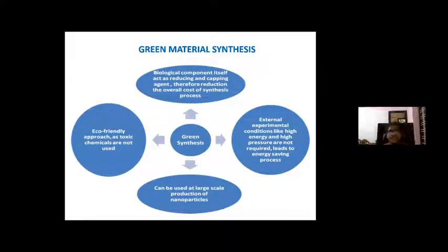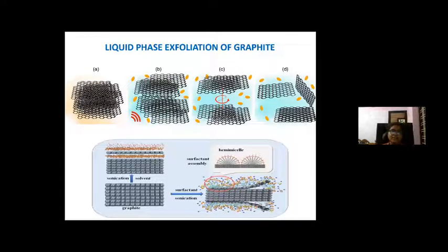Instead, the most preferred method for graphene synthesis is via green methods. We all know that green synthesis adopts an eco-friendly approach, and toxic chemicals are not used there. This method is already extended for the large-scale production of many nanoparticles, including graphene. Here, we prefer the liquid phase exfoliation of graphite for the production of graphene. But usually, for liquid phase exfoliation of graphite, toxic solvents such as NMP, N-methyl pyrrolidone, or DMF, dimethyl formamide, are used. And this is not a green technique. Also, the yield of graphene is low.